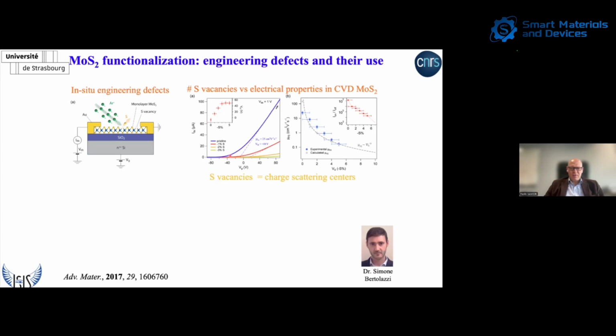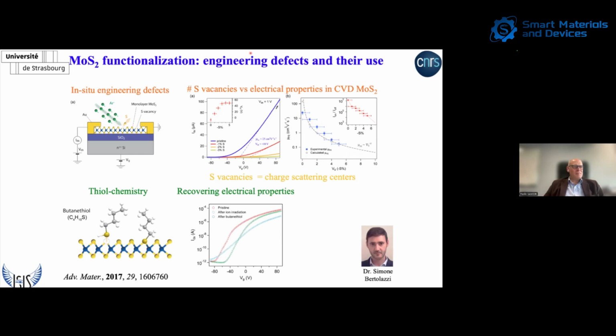And it depends also on the type of two-dimensional material you want to play with and how strongly the atoms in the lattice are bonded. So here we use the argon beam of the XPS. And you can see that by doing this, you increase the defectiveness within your crystal, which is accompanied by a drastic decrease of the current through a junction, and you can plot this as an exponential decrease of the field effect mobility with the increasing number of sulfur defects. And now, you're creating defects that are scattering centers for charges, but these are also reactive sites, as I said, and they can be healed with a thiolated molecule.